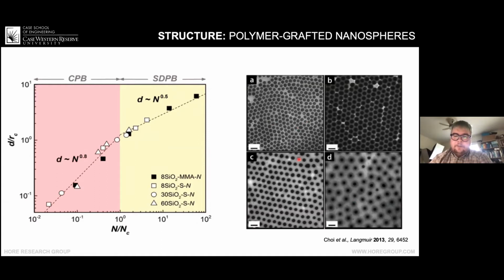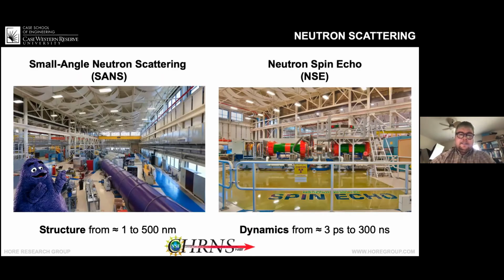Other people have also done it by looking at TEM images and measuring the thickness of the brush that they can observe. So we take a different approach to this, and we use neutron scattering. If you've never seen these instruments, this is at the NIST Center for Neutron Research outside of Washington, DC. There's a nuclear reactor back here that's 20 megawatts, using high enriched uranium to enhance the number of neutrons that come out. This instrument here is 30 meters long, and it's the small angle neutron scattering instrument for structure, painted this nice bright purple.